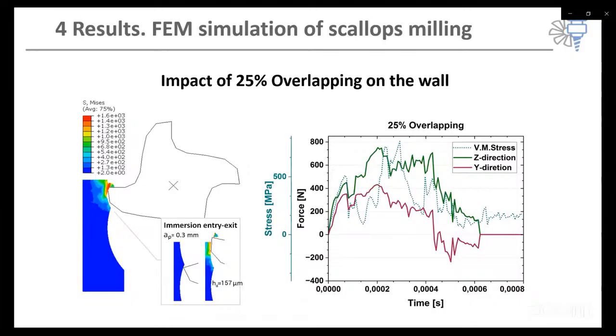In contrast, this slide shows the effect of only 25% overlapping. Here, the residual scallop height remains high, about 157 microns, which leads to uneven force application and more aggressive cutter impact. This configuration increases the horizontal force component Fy, which acts in the direction of minimum stiffness, making the wall vulnerable to bending.